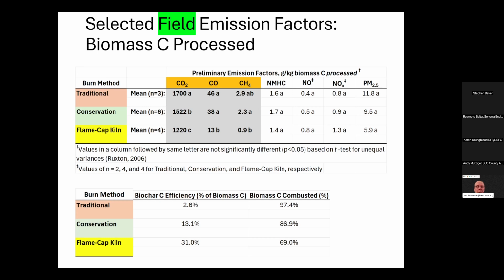And looking at the bottom again, now you're seeing biochar carbon efficiency ranging from about 3% again for traditional, but up to 31% for the flame cap kiln. And the biomass carbon combusted is decreased by those same amounts. So we think when you're looking at this from the standpoint of the biomass, how much of that biomass ended up in the atmosphere, in the case of the flame cap kiln, only a little more than 2/3 of the carbon ended up in the atmosphere.